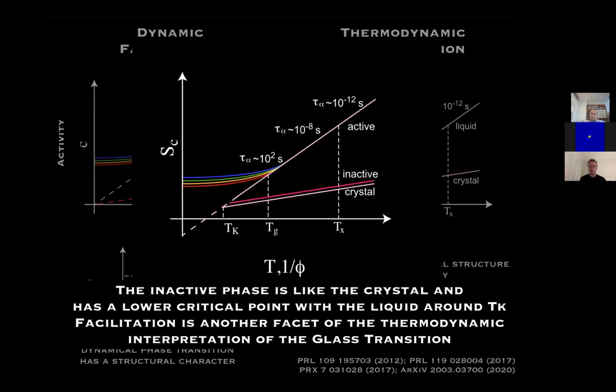So if I now put these two things together, then what I have is the following. We have measured the configurational entropy of the inactive phase, and it looks rather as shown in this sketch. The configurational entropy of the inactive phase is a little bit higher than the crystal, but not much. And the configurational entropy of the active phase is very much higher. The active phase being the normal liquid, but it drops, and we have a meeting of these phases. So the active phase and the inactive phase meet. Actually, it'll be bounded by the Kauzmann temperature, but it's close to it, at least in the model I'm talking about here. And then the crystal would hit the inactive phase at the Kauzmann temperature.